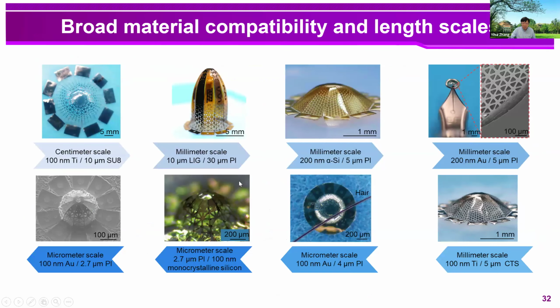And because this method is fully compatible with the 2D fabrication approaches, this method can be used to assemble 3D surfaces in a variety of materials like graphene, the laser-induced graphene, the polymers, the monocrystalline silicon, and also polycrystalline silicon, as well as other materials. And the length scale also range from a few hundreds of microns to centimeter scale.